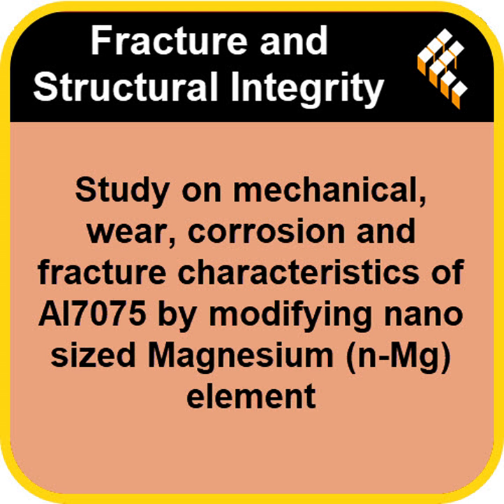And they tested this. They did. They submerged samples for 30 days in Pondicherry seawater. The visual evidence was stark. The SEM analysis showed dramatic, localized corrosion pitting, cracks, uneven surfaces everywhere. It was a clear confirmation that the passive coating had just collapsed. And the culprit here is something you called microgalvanic activity, right? Can you simplify that for us?